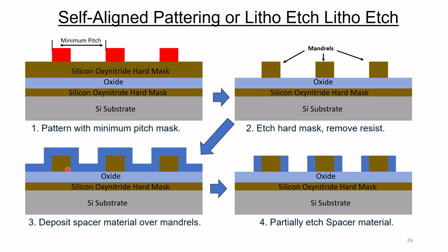Now what we do is we come in and we deposit a spacer material that goes over and around the mandrels. And this is very similar to the spacer materials used to create spacers on standard planar MOS devices to the left and right of the gates. Now we have this spacer material deposited, and now we do an etch. And the etch is coming down, and it etches away this stuff equally, but because it's thicker around the sides of the mandrels, it leaves the spacer around the sides of the mandrels, but clears it out on top of and between the mandrels.